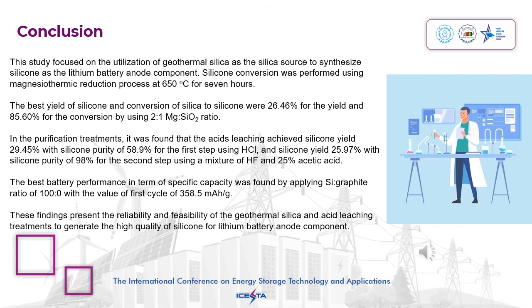The best battery performance in terms of specific capacity was found by applying a silicon and graphite ratio of 100/0, with a value for the first cycle of 358.5 mAh per gram. These findings present the reliability and feasibility of geothermal silica and acid leaching treatment to generate high quality silicon for lithium battery anode components.